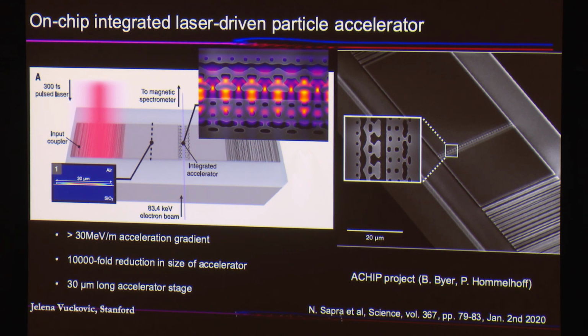So what we are doing here is replacing microwave or radio frequency fields with optical fields, and building stages of an accelerator that would perform accelerations on the particles. But you can't really directly shrink the traditional accelerator because metals would not work as well, and components would not work as well if you just directly miniaturize them. You essentially have to structure the electric field, and in this case, we're structuring a piece of silicon in order to design the right electric field profile that would accelerate electrons.